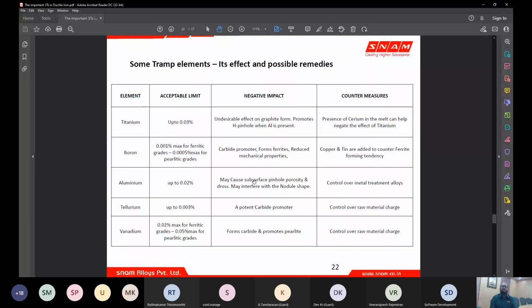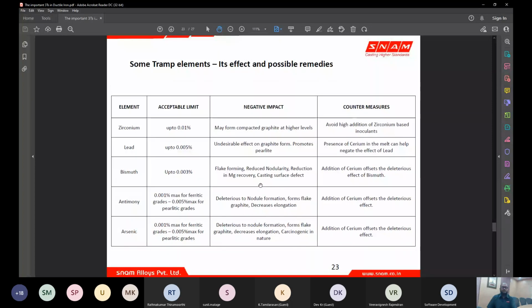And vanadium, we know, is a mild pearlite promoter and a very strong carbide promoter. In different grades, a different amount of vanadium is allowed, and this again comes from your steel or the raw materials being added. And this is zirconium. Zirconium, as we know, is a strong nucleating element. There are zirconium based inoculants available, but there is a limit for zirconium.